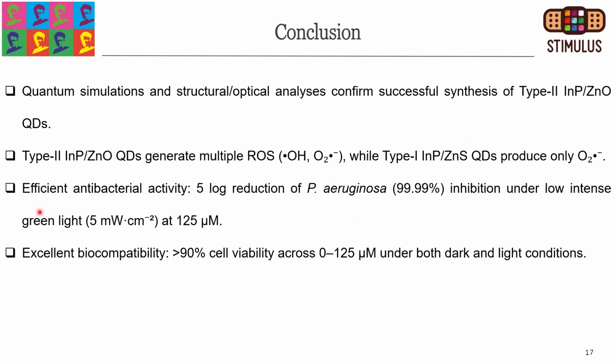And we also observed that these quantum dots show efficient antibacterial activity, almost a 5-log reduction of Pseudomonas aeruginosa, under low intensity green light, which is 5 milliwatt per centimeter square. And we also observed that this quantum dot shows excellent biocompatibility, about 90% cell viability across 0 to 125 micromolar under both dark and light conditions.